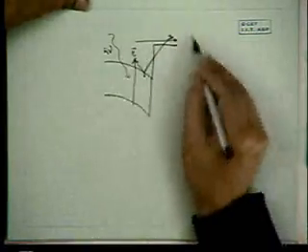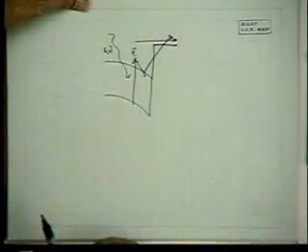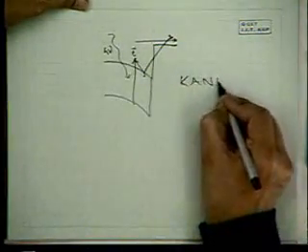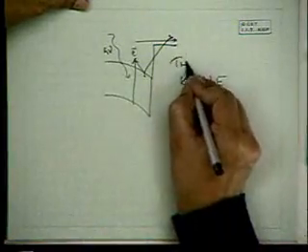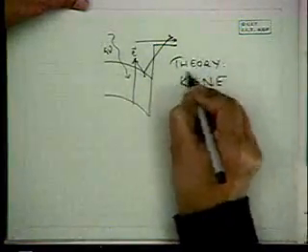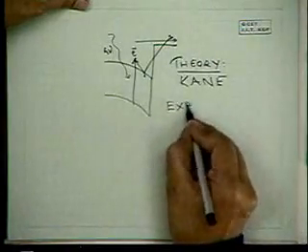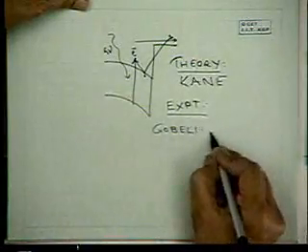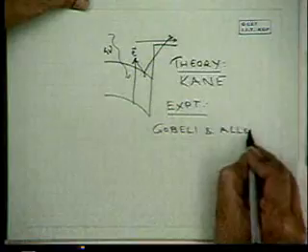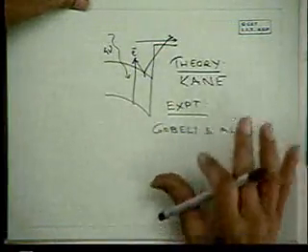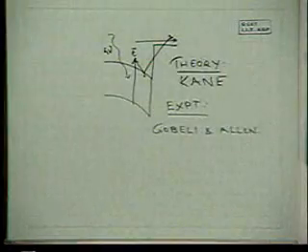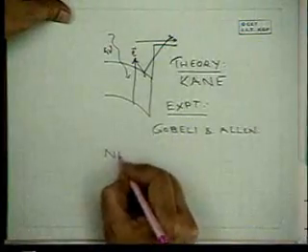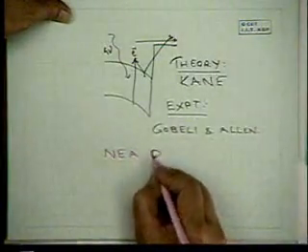Okay. So all these have to be considered in the actual process of photoemission, and this has been analyzed in great detail. The theory is by Kane, and the experimental work was done by Gobeli and Allen at Bell Labs in the early 60s. So the processes are fairly well understood, and this has really resulted in these remarkable NEA, negative electron affinity photocathodes.